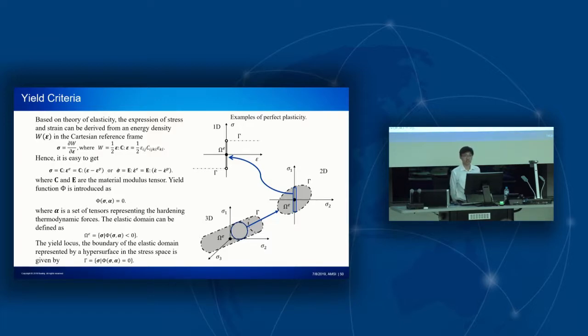But when the yield function is equal to zero, it defines a hypersurface in a high dimensional stress space, and that surface we call the yield surface. Only when the stress stays on top of the yield surface, the plastic deformation will happen. For a very simple example, if we consider perfect plasticity, isotropic von Mises criteria, the yield surface looks like a cylinder in the three-dimensional principal stress space, an ellipse in the two-dimensional principal stress space, and 2 points in one-dimensional principal stress space.